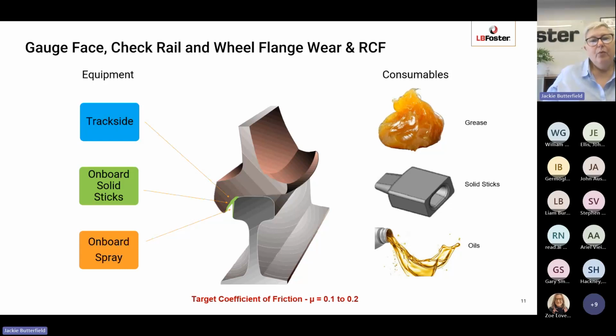Here we are aiming for a coefficient of friction, ideally as low as possible, but somewhere around 0.1 to 0.2. If you think back to the diagram where I talked about adhesive wear, we're trying to keep the surfaces apart and as separate as possible so that those asperities, those peaks in the rough surface, don't get a chance to bond together and rip apart and form that wear debris. So we're trying to lubricate as low as possible to prevent wear damage.